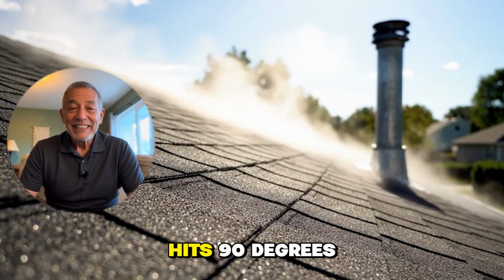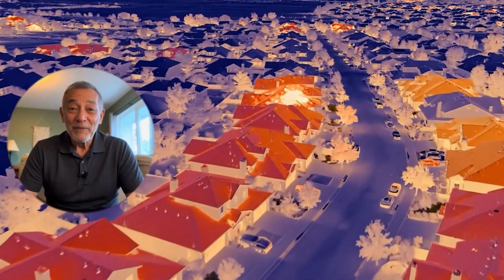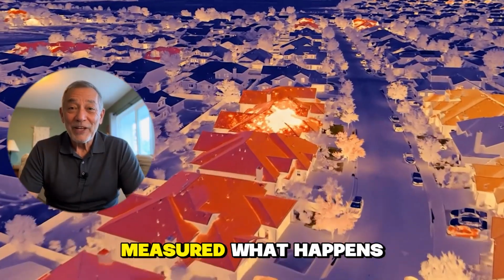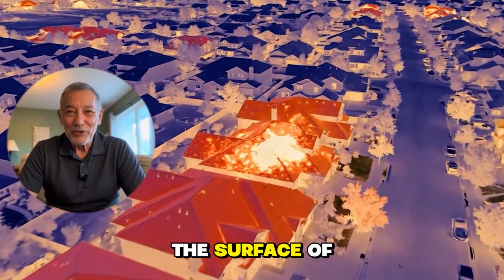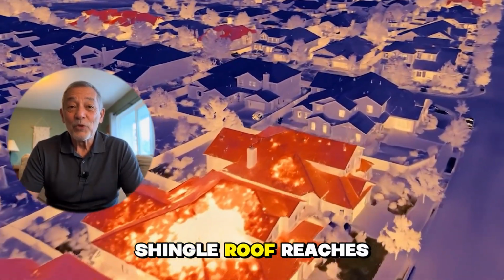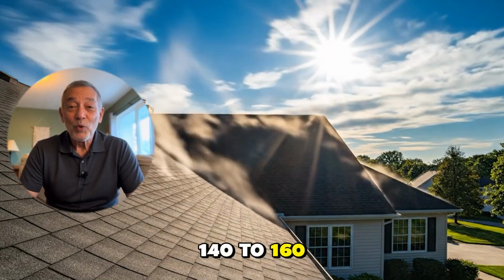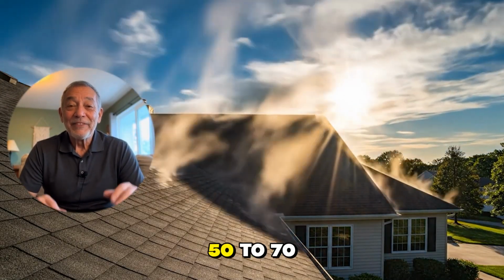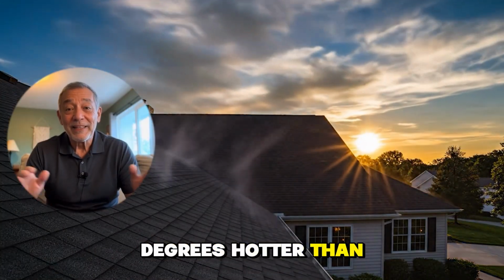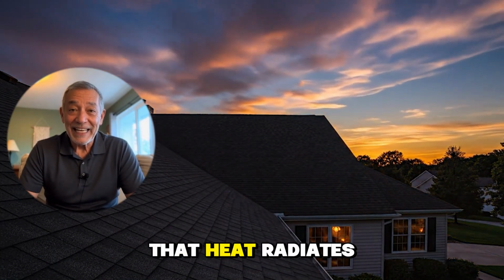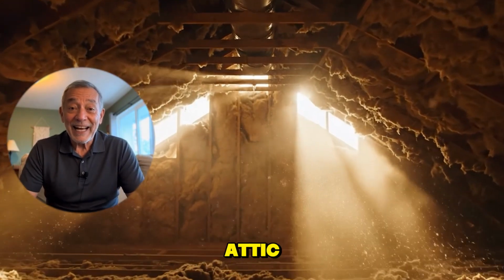Ambient air hits 90 degrees Fahrenheit. Oak Ridge National Laboratory measured what happens next. The surface of a dark asphalt shingle roof reaches 140 to 160 degrees, 50 to 70 degrees hotter than the air around it. That heat radiates downward into the attic.